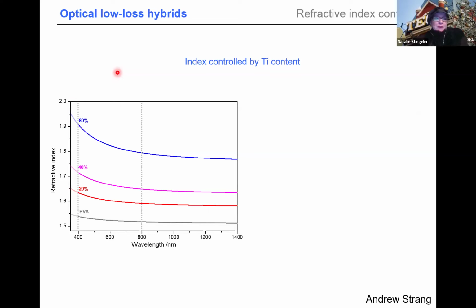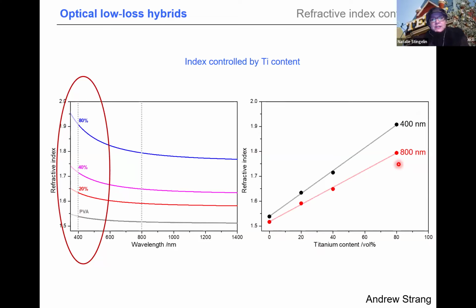Clearly, we needed to know about the refractive index. We want to have a high refractive index material. For this, we did ellipsometry, and not surprisingly, the higher the amount of your titanium oxide hydrate polymer, the higher the refractive index. And it's actually a very homogeneous material, telling us we don't have a nanocomposite, but really this molecular hybrid.